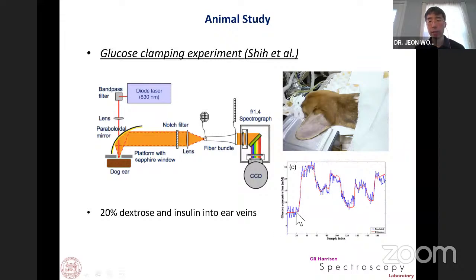So this red color is showing our measured value, and this blue curve is showing our predicted value. As you can see, our prediction is following the reference blood glucose concentration very well. And similarly, as in the previous experiment, we were using a paraboloidal mirror and also a fiber bundle with a lot of fibers inside of the one fiber bundle. And these fiber bundles are linearly aligned to the imaging spectrograph.